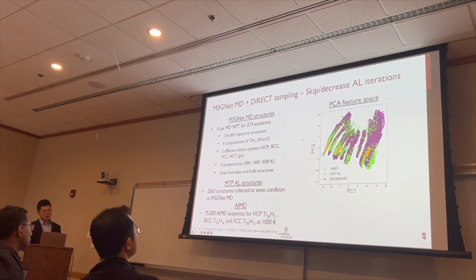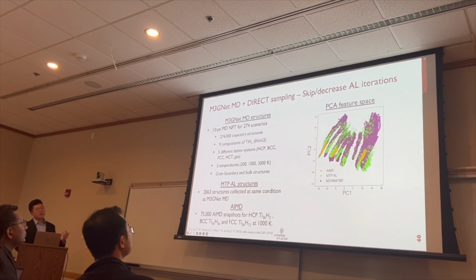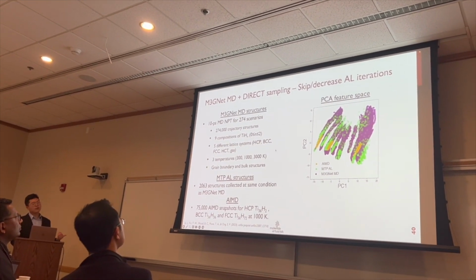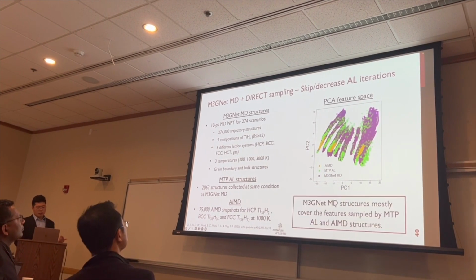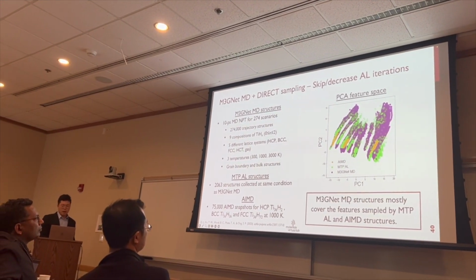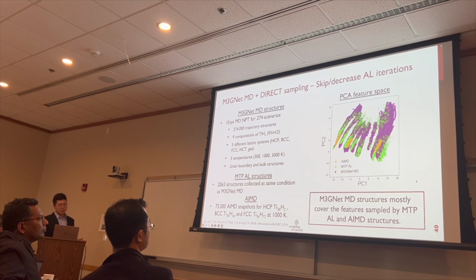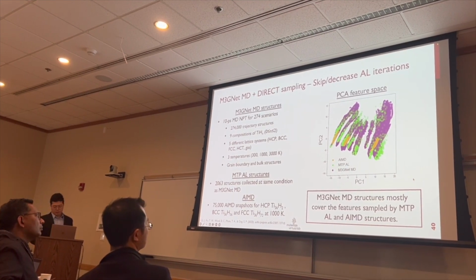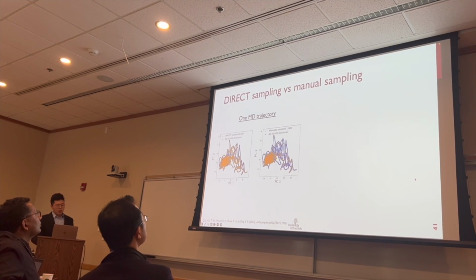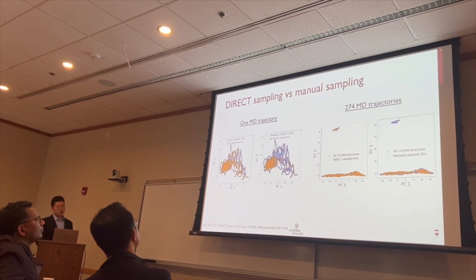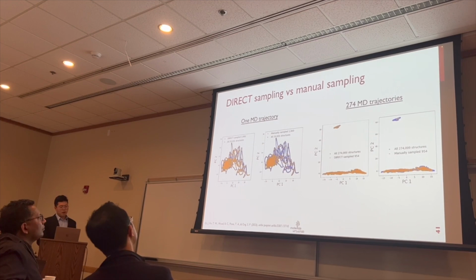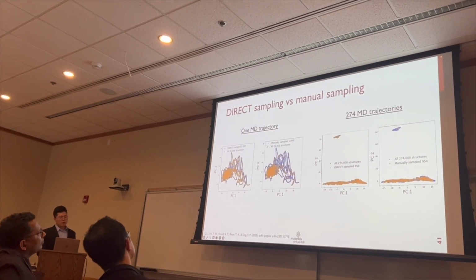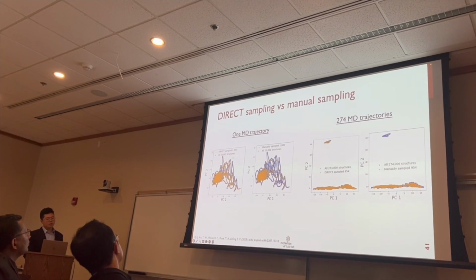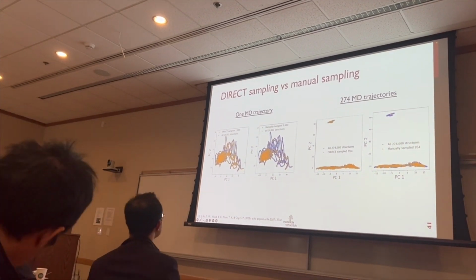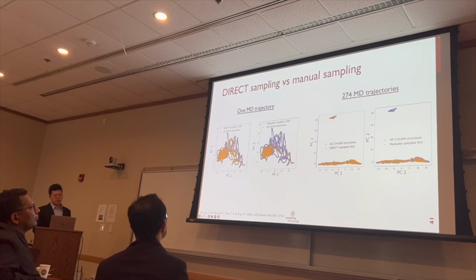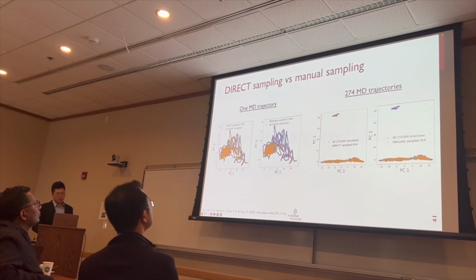In this PCA feature space, we can visualize the feature space covered by these three different data sets. What we see is that M3GNet MD structures can mostly cover the features sampled by MTP active learning and by AIMD structures. And we use direct sampling to sample structures from the M3GNet MD trajectory. We can see that compared with manual sampling, direct sampling can better cover, again, those relatively rare regions of the feature space, which is the same case for these plots.